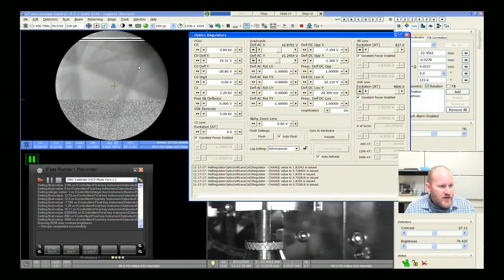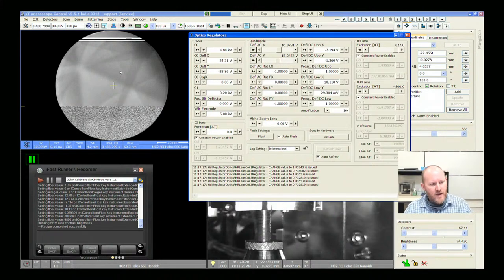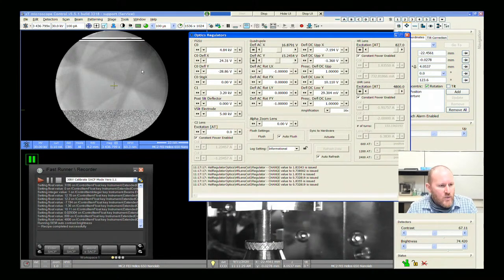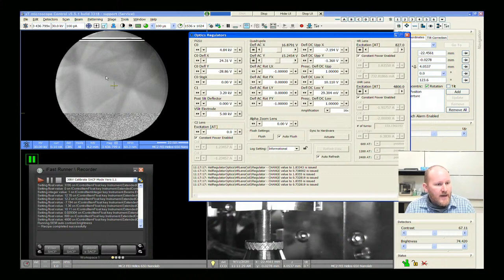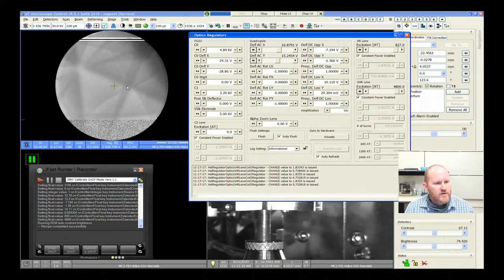We can clearly see our channeling pattern. Effectively what an SACP is — it's a type of ECP, an electron channeling pattern. When you have a fixed crystal lattice and you're rocking the beam with respect to the lattice, we get a modulation of the channeling strength, and that's what we're imaging here. I'm not sure what this orientation wafer is. Let's go back and maybe I'll go to some others to see if we get something that's a little more obvious. We also have the option of making this full screen.